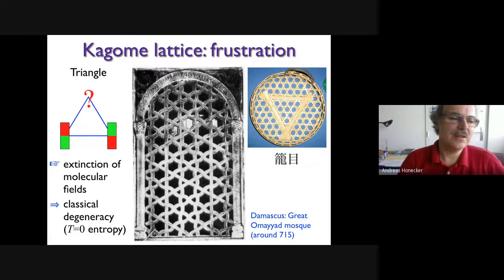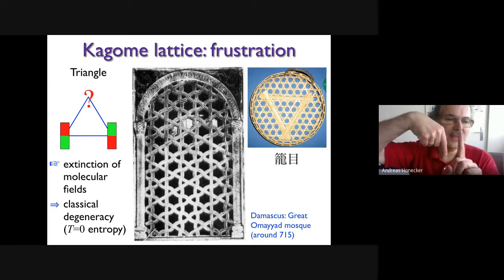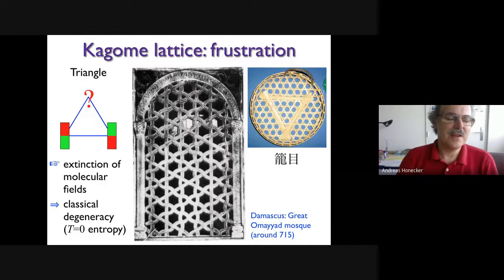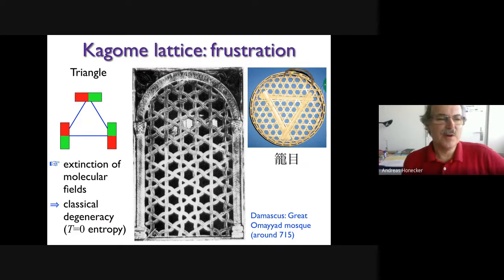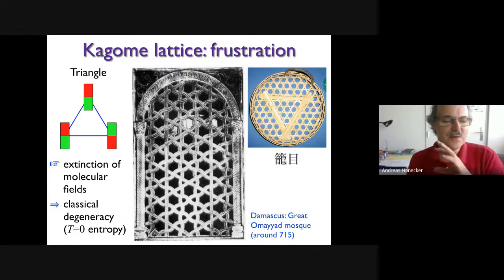The standard example for illustrating frustrated magnetism is the triangle. The point is, a triangle has 3 corners, and if you put an antiferromagnetic interaction on it, you can align 2 spins in antiparallel. That is possible, but if 2 spins are antiparallel, then the third one cannot satisfy both any longer, so it doesn't know where to point. Any direction of the spin will do. That means that basically at the molecular field level, there's a cancellation of molecular fields, and you get a classical degeneracy. Of course, we know that this is not the solution for the Heisenberg triangle, where you get a 120-degree structure, but at least for the Ising model, that would be it.